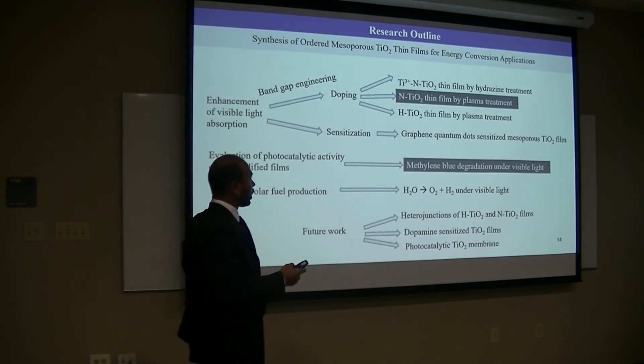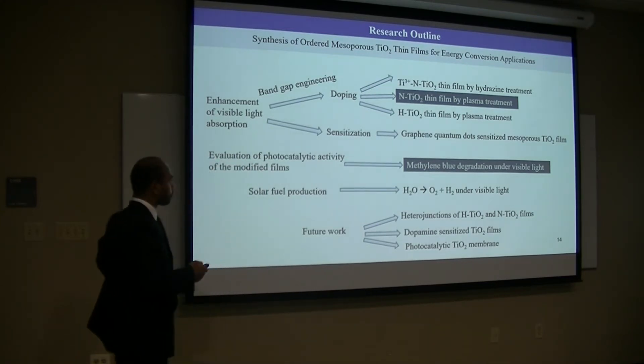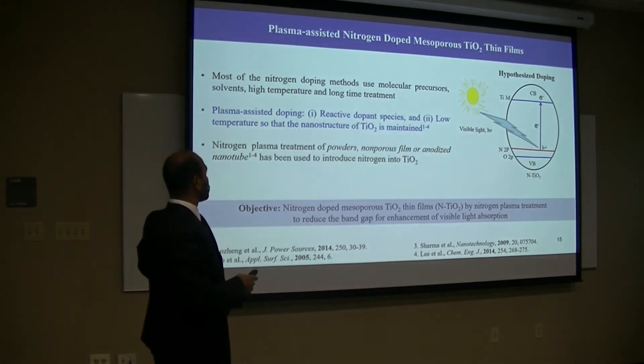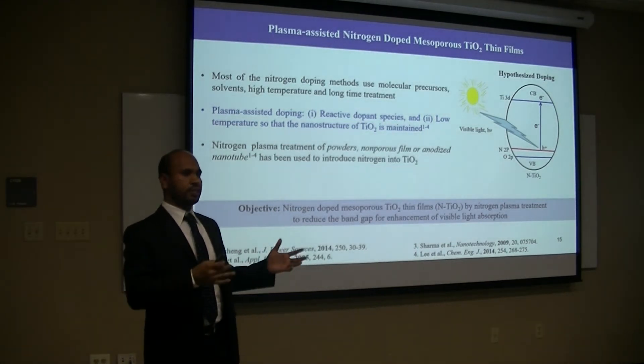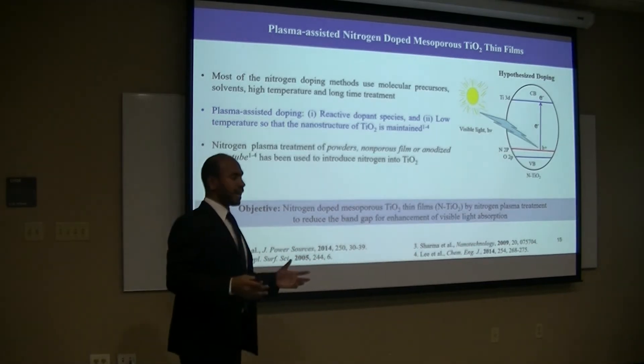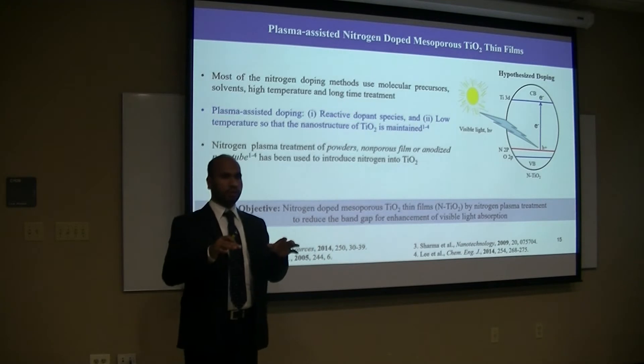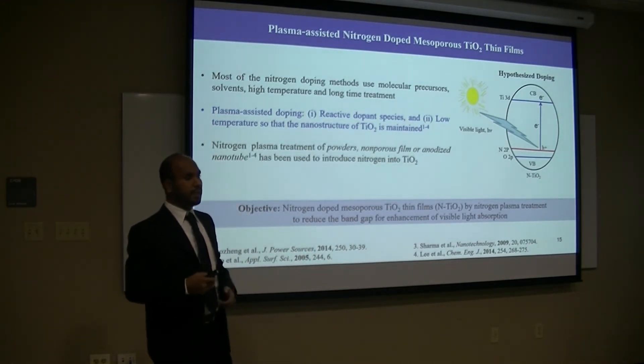For nitrogen doping, we developed another method: plasma-based treatment. As we saw in the previous chapter, and as is typical, all doping methods use either molecular precursors or solvents or high temperature or long-term treatment, which causes trouble with the nanostructure. Plasma-based doping stands out because it produces very reactive doping species, and most importantly it operates at relatively low temperature so that the nanostructure of our materials can be maintained.